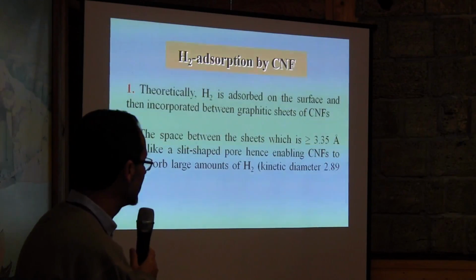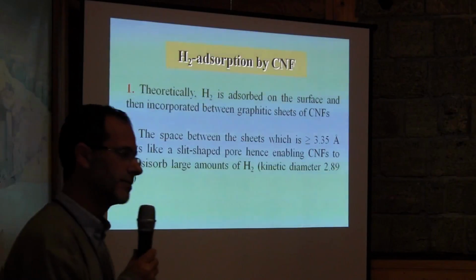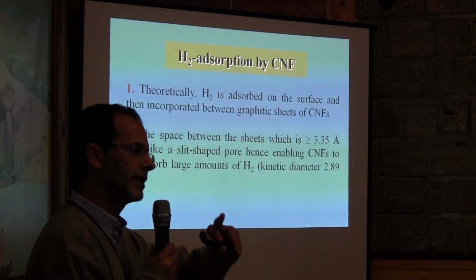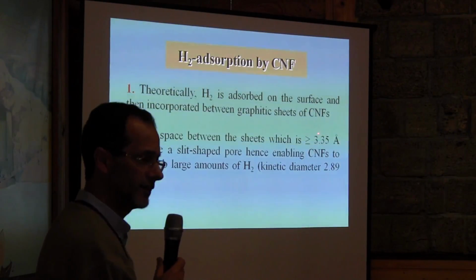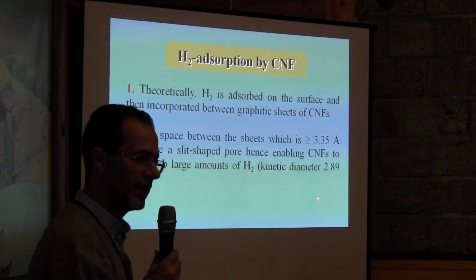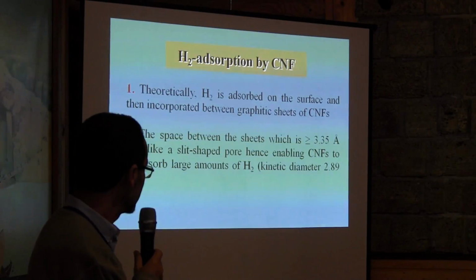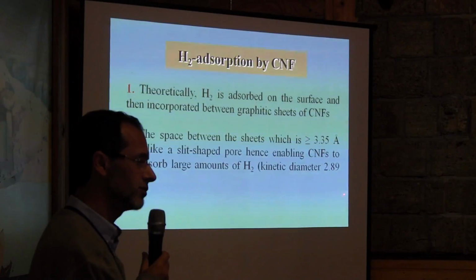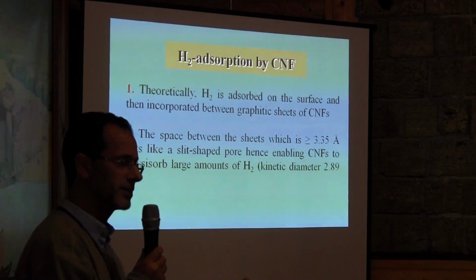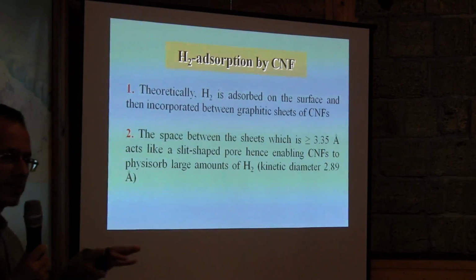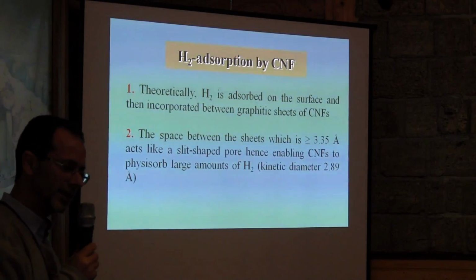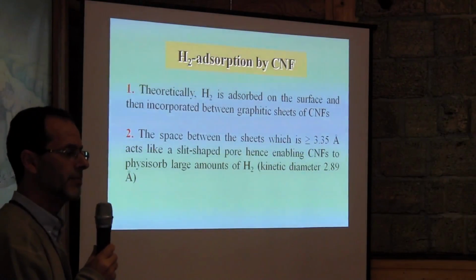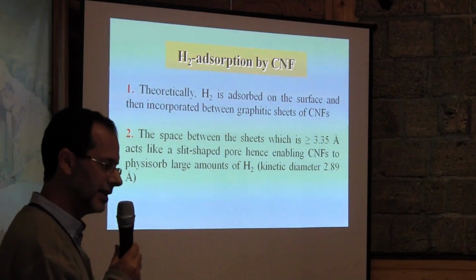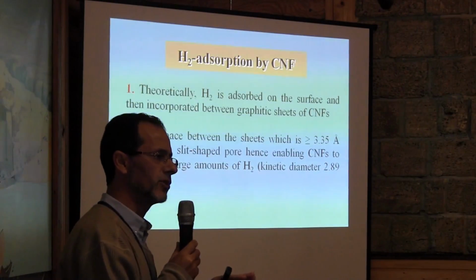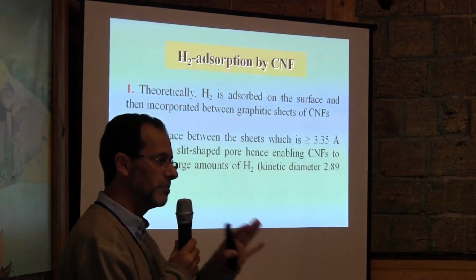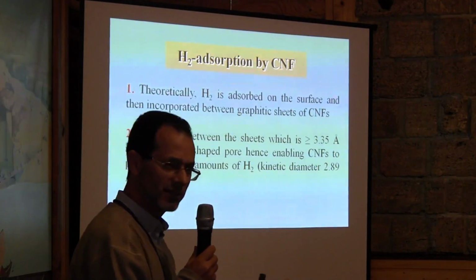As I said, why are we interested in carbon nanofibers? Because the distance between carbon layers is about 3.35 angstrom, and the molecular diameter of hydrogen molecules is 2.89. So we expect from this that hydrogen can be intercalated between carbon layers. At that time, we saw many papers publishing theoretical investigations, again DFT calculation, that carbon nanofibers can absorb or physisorb, whatever. We don't know the mechanism yet at that time. About 60%. This is huge.